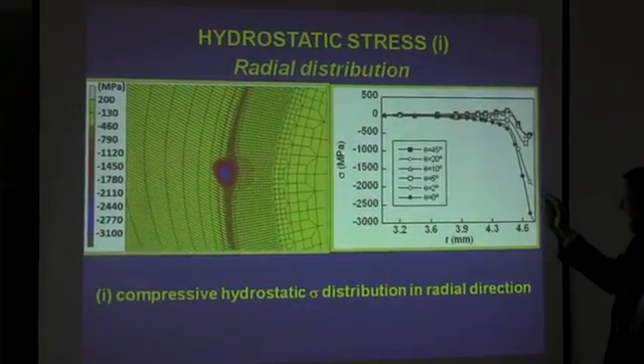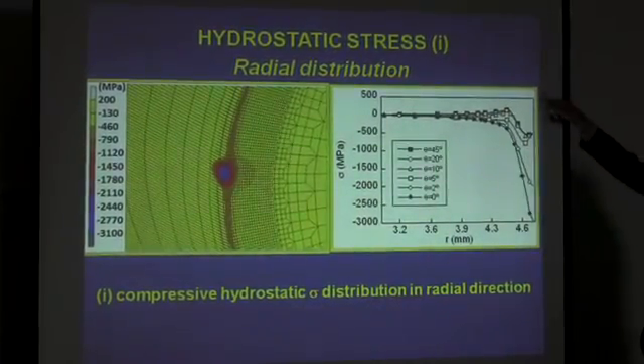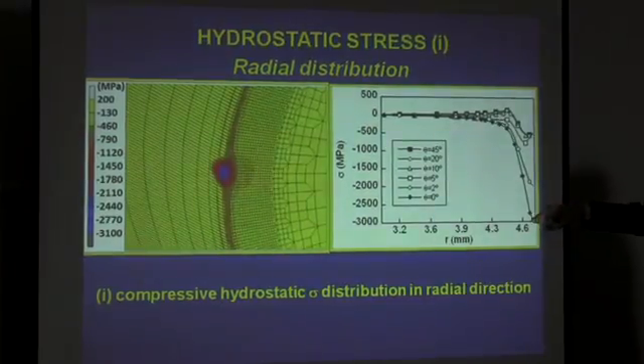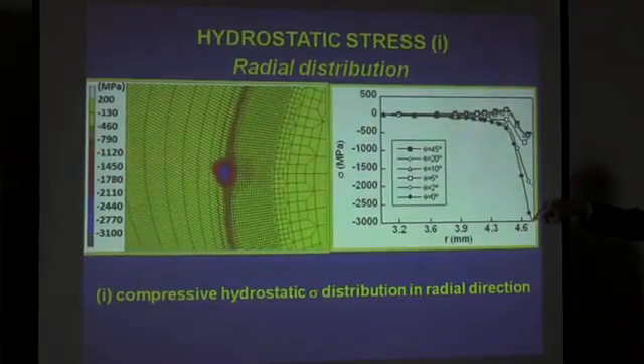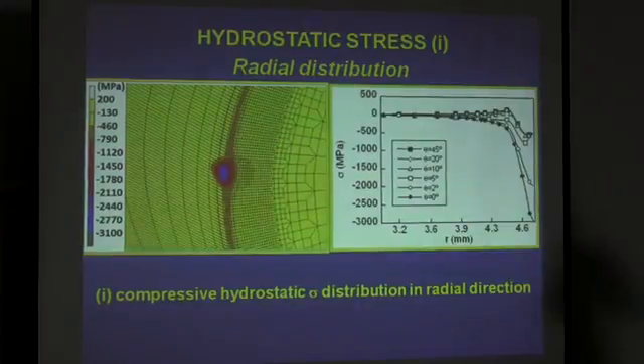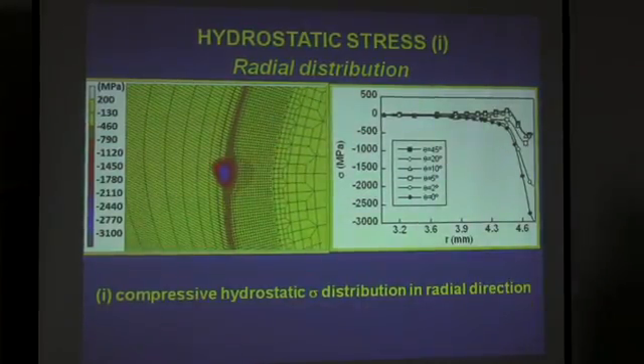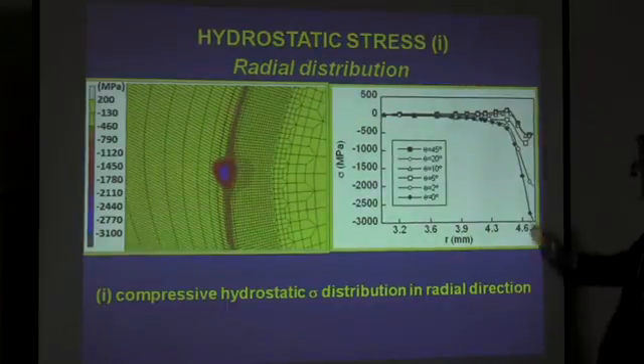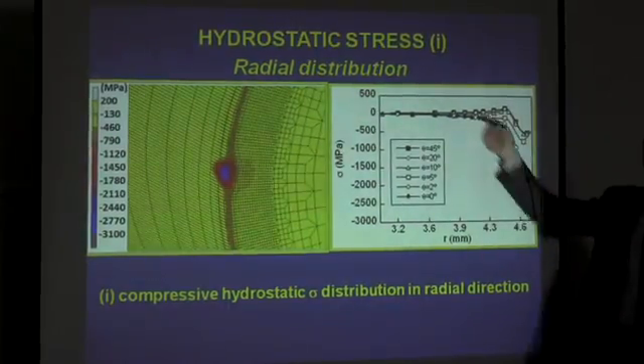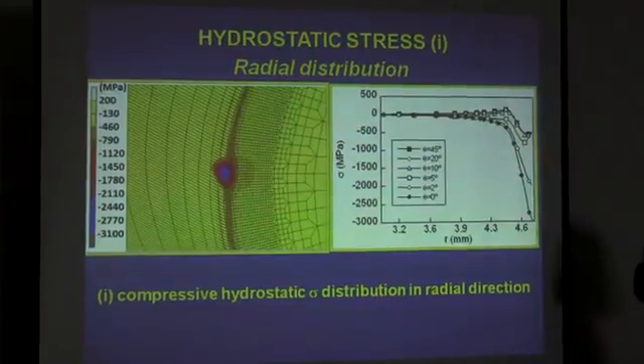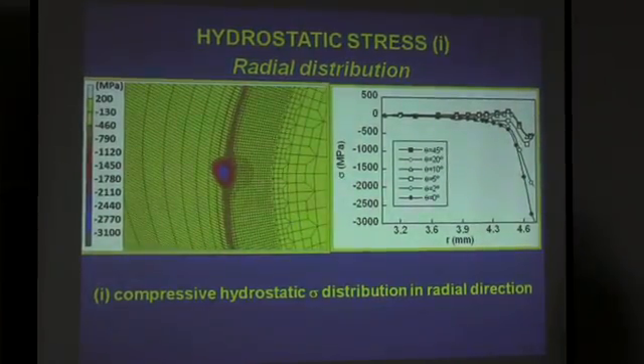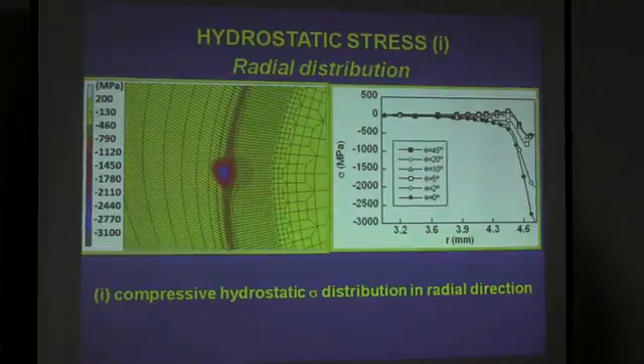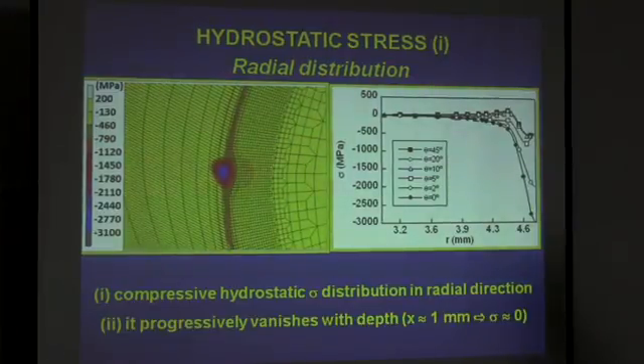The inward gradient is positive, but the boundary condition, the hydrostatic stress at the boundary is strongly negative. Then that's contradictory. On one hand, we have a small amount of hydrogen supply because of this negative hydrostatic stress at the boundary, but this small amount is strongly pumped because of this very pronounced hydrostatic stress gradient, inward gradient, positive toward the inner point, which is predominant, we are going to say, in the distribution of concentration.